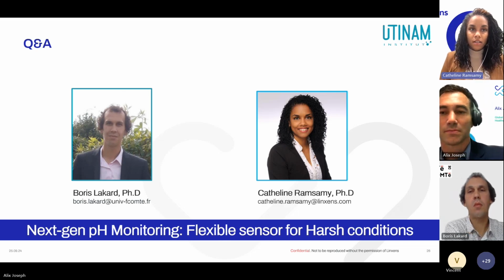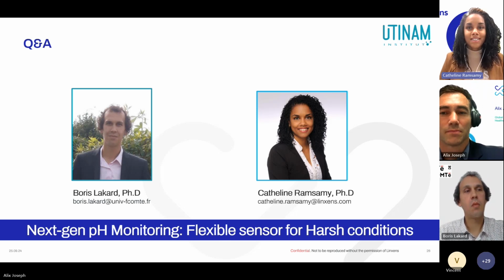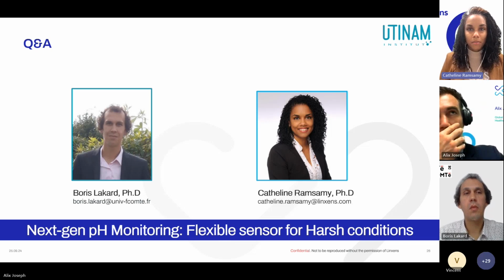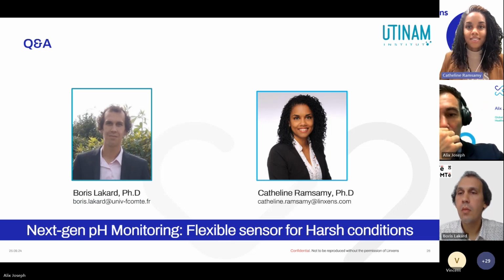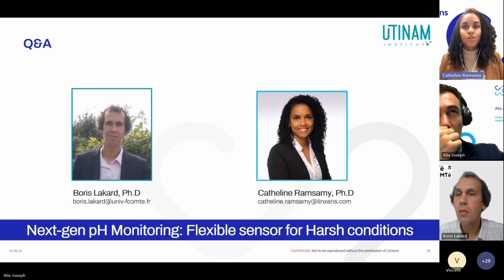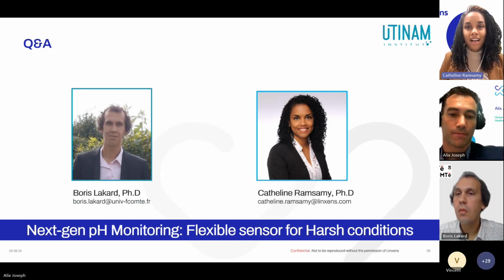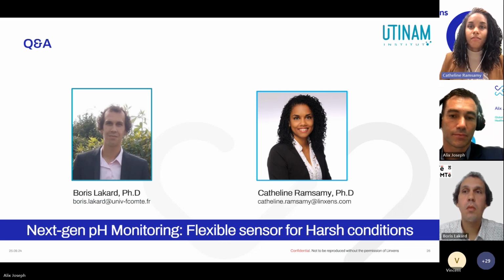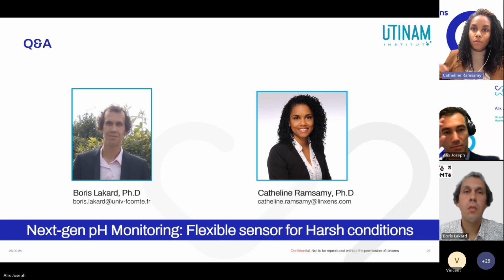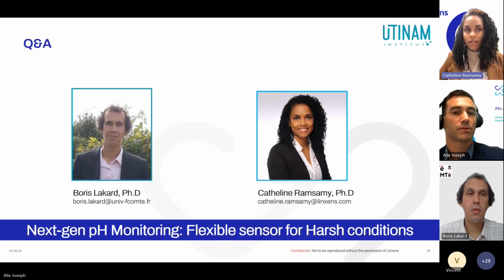But after that, the requirement on the reference electrode property will depend on your specification, because we know that at the moment on the market, you will have pseudo-reference electrodes, but you will not have a very stable reference electrode like we can find in the lab with the real probe that you have in the lab.